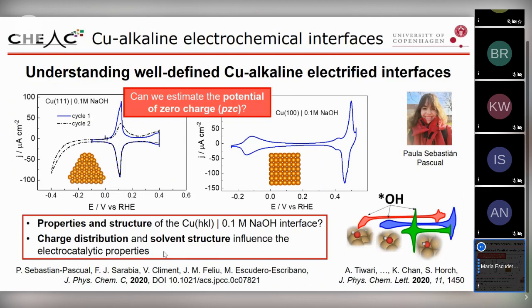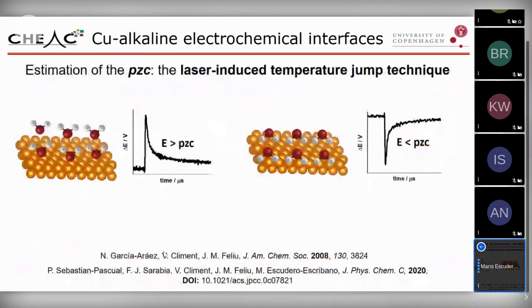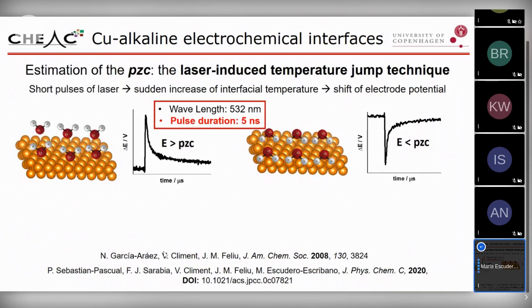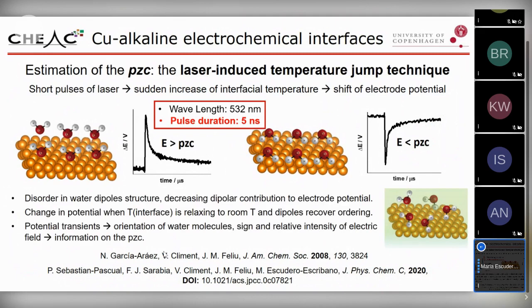So we thought this was interesting to investigate, and Paula did a research stay in Alicante to use the laser-induced temperature jump technique. I won't go into detail, and I'm not an expert in this technique, but in summary, what this does is apply very short laser pulses, like 5 nanoseconds, that give rise to a sudden increase in the interfacial temperature, and that will shift the electrode potential. So this potential shift will induce a disorder in the structure of the water dipoles, and thus decrease the dipolar contribution to the electrode potential. And then as the temperature of the interface relaxes to room temperature, the dipoles recover ordering. So this is a positive transition, and this is a negative transition. It recovers ordering, so you will have the ordered water molecules.